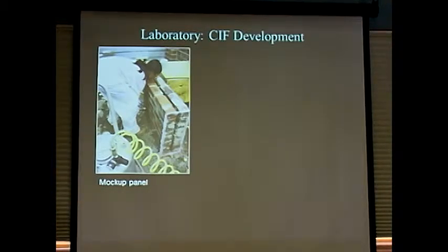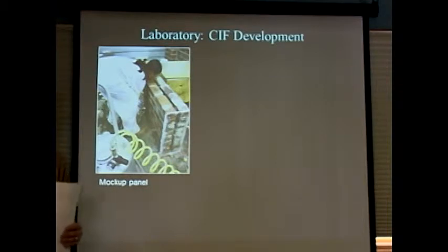And the key to developing these mixes is that it has to be compatible with the existing masonry. It's actually really easy to come up with a material that's super strong and flowable and gets into tiny cracks and fissures. The challenge is coming up with a low strength, high compressibility, low elastic modulus material that is compatible with historic brick. And vapor permeability also comes into play. And just like we do with mortars, we tend to stay away from high cement injection materials. We go with a lot of high lime materials, admixtures, and we'll see how that works in our little demonstration in a few minutes.